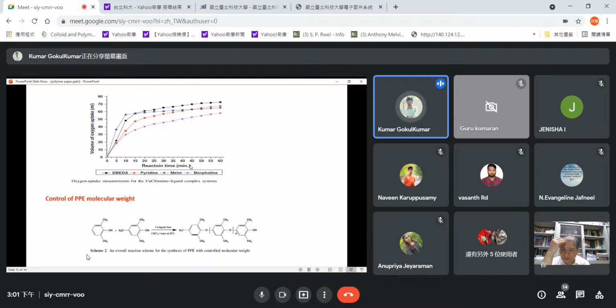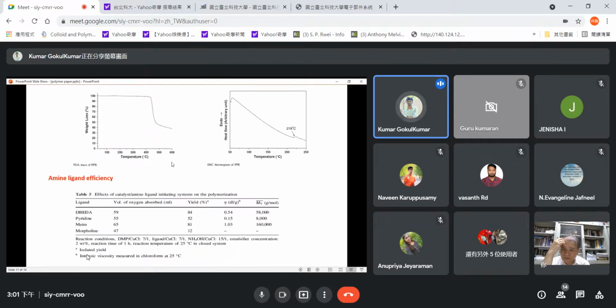The oxygen uptake measurements were performed every 5 minutes for 1 hour. This data is plotted in this figure and in Table 5. The pyridine showed good reactivity, and the copper chloride ligand complex system is a solution polymerization; pyridine and morpholine are not proper ligands for our heterogeneous system.